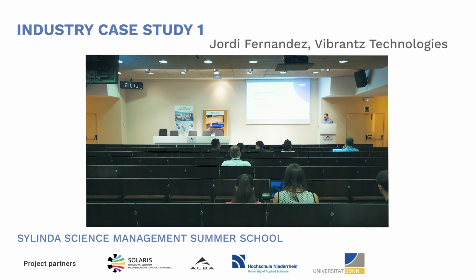Okay, thank you. Well, I want to say ultramarine is a stable pigment. It depends on the environment, of course. For example, it's not acid resistant, but we developed an acid resistant grade to cover the ultramarine blue with something that gives some resistance against the acid. And with clays, more or less the same. We have an especially developed solution for the clays and cements sector.